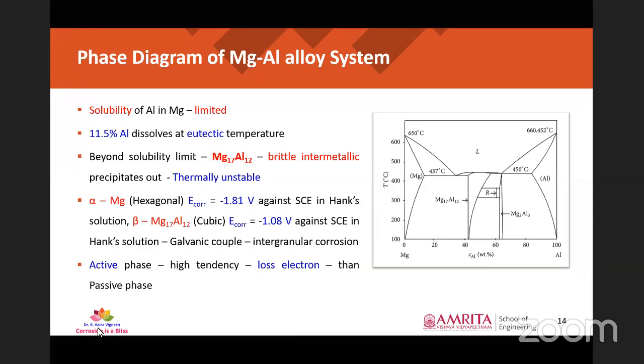Coming to the corrosion perspective, the alpha magnesium, which is the primary phase of the alloy, has a corrosion potential of minus 1.81 volt against standard calomel electrode in Hank's solution, and the beta phase, which is the secondary intermetallic phase present in AZ91 alloy, has a corrosion potential of minus 1.08 volt against standard calomel electrode in the same Hank's solution. When two phases in the matrix have a wide gap in corrosion potential, this leads to a galvanic coupling effect, which in turn leads to intergranular corrosion. So we have to ensure that intergranular corrosion is minimized while we fabricate surface composites. Added to that, the active phase has a high tendency to lose electrons compared with the passive phase, which results in a high corrosion rate. So we have to engineer this parameter also so that we get the desired corrosion rate of less than 0.5 mm per year.